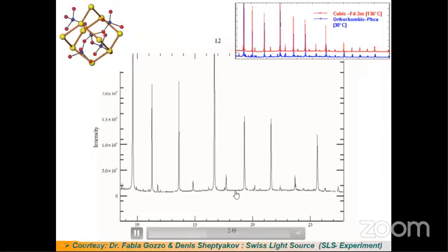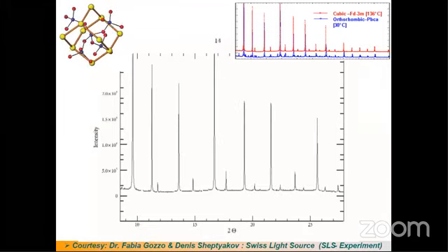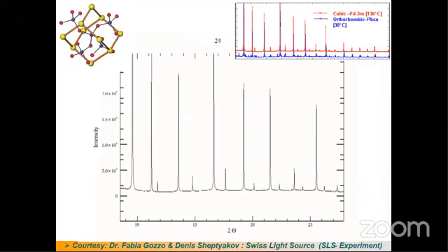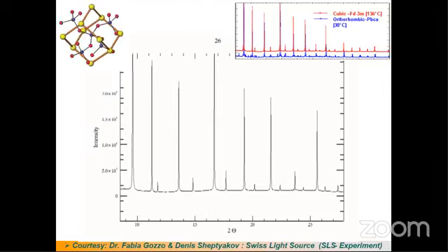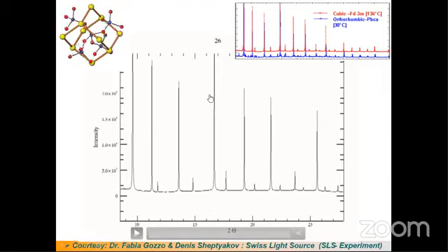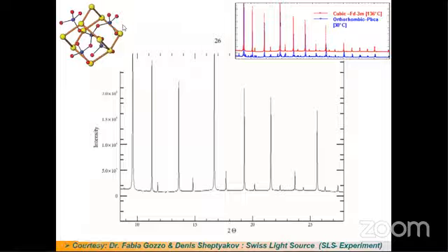Now, the temperature at which these rotor molecules start functioning is the temperature where the phase transformation is taking place. It's a very well resolved pattern, as you can see in the slide. This directly depicts that the phase transformation is taking place, and on the top there are a number of diffractograms that I used for the generation of that picture using the Powder 3D software of Robert Dinnebier.